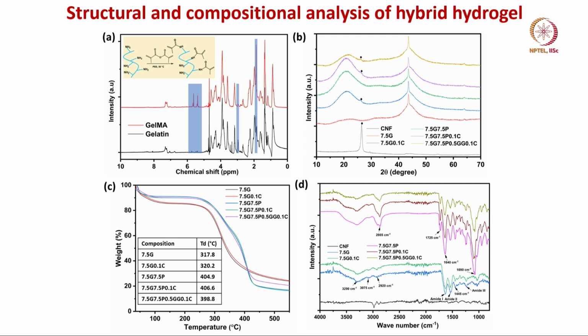So, when you start with the gelatin to GELMA, this conversion process is monitored, or the signature of this conversion can be recorded using proton nuclear magnetic resonance spectroscopy, NMR, and you can see there is something called HA, HB, HC. I think I have mentioned before HA, HB, HC, and this chemical shift. You can clearly see this particular NMR band